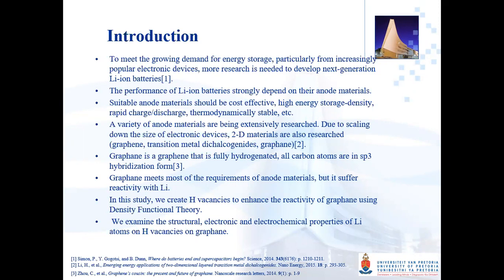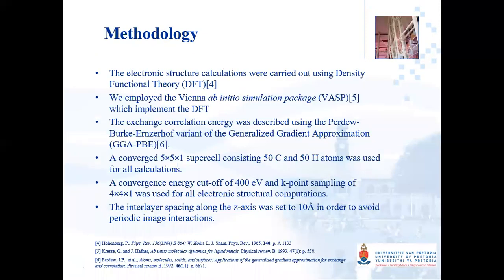Graphane is a material that is fully hydrogenated with all carbon atoms in sp3 hybridization form. Graphane meets most of the requirements of anode materials, but it suffers from low reactivity with lithium. In this study, we create hydrogen vacancies to enhance the reactivity of graphane using density functional theory. We also examined the structural, electronic, and electrochemical properties of lithium atoms on hydrogen vacancies on graphane. The electronic structure calculations were carried out using DFT, employing the Vienna ab initio simulation package (VASP), and a converged 5x5x1 supercell was used for all calculations.